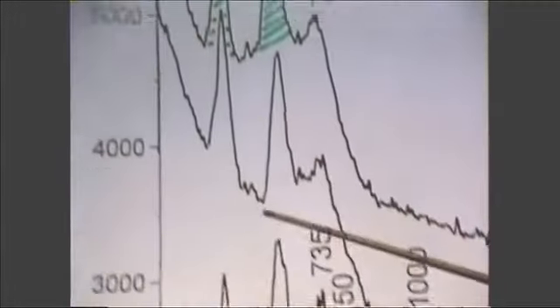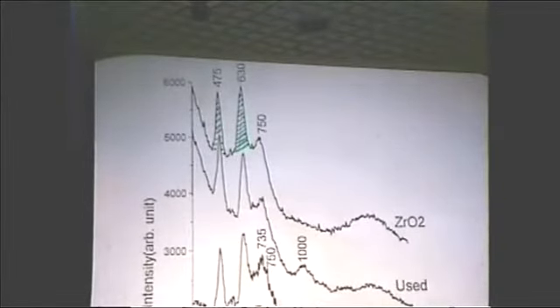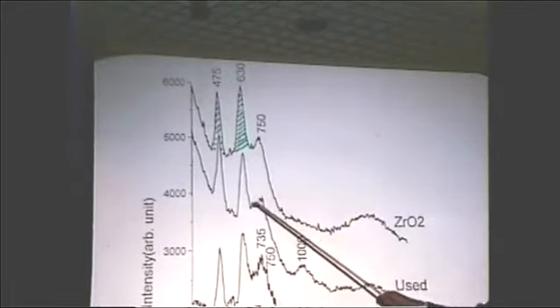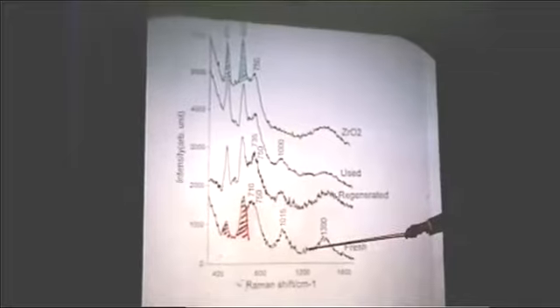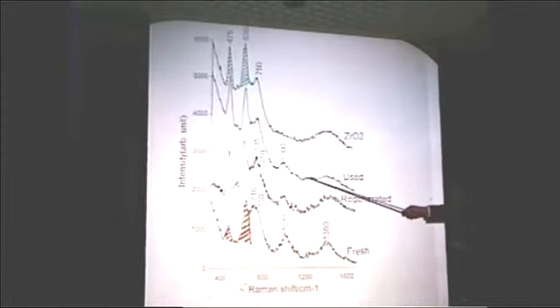So this catalyst died, but it did not die because it was coked, because there's no coke. But what we do find is that if we look at the spectral region here, there have been some pronounced changes in the spectral region down here, which is representative of the zirconia. In fact, if we compare the spectrum that we measured for the dead catalyst with the monoclinic form of the zirconia, we have almost an identical pattern of intensities between the dead catalyst and the monoclinic form of zirconia, which is known to be the inactive form of zirconia. So what we seem to have seen here is a transformation between the tetragonal form and the monoclinic form of zirconia, and that in fact is why this catalyst died rather than that the catalyst was coked.